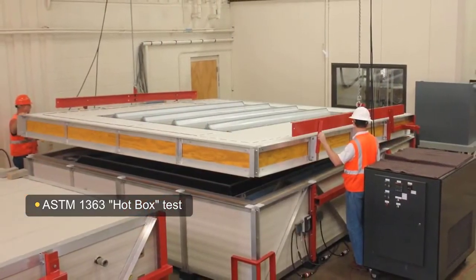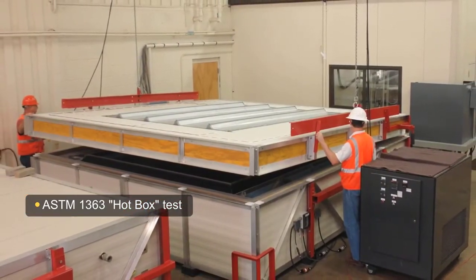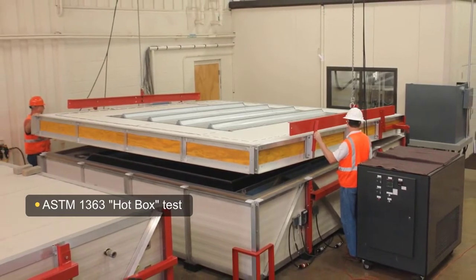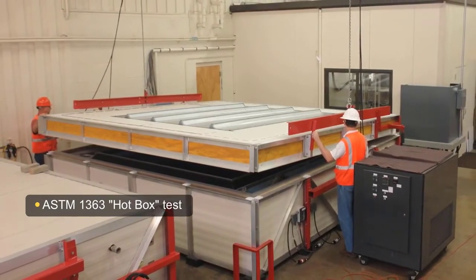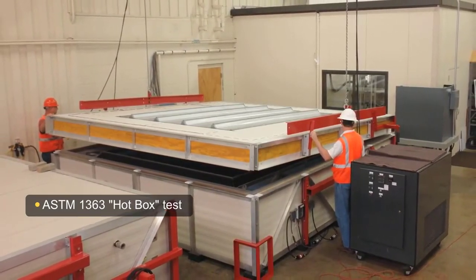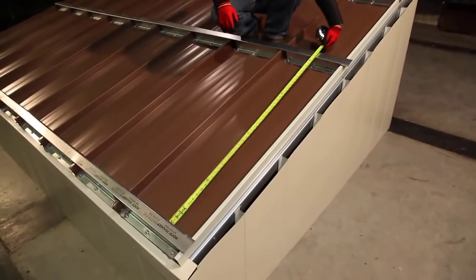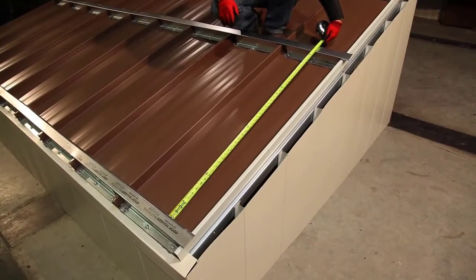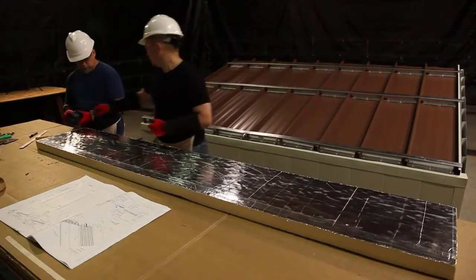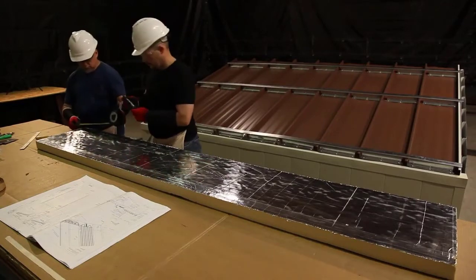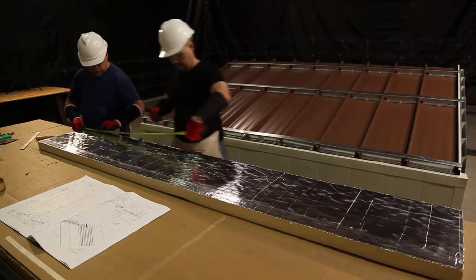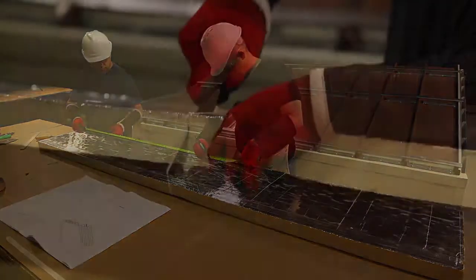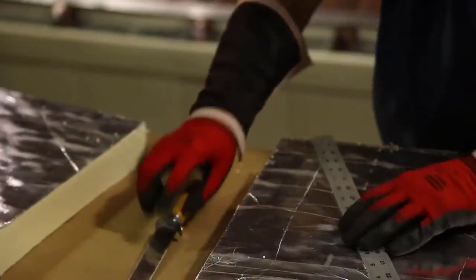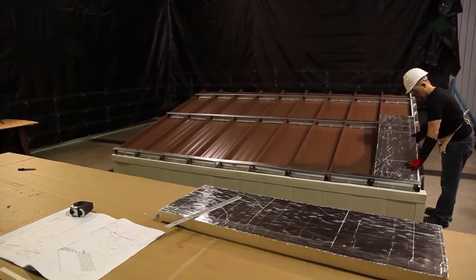A key result of this research showed that it is important to recognize how insulation systems are constructed, rather than looking only at the total R-values of the insulation layers. On our mock-up, with the sub-purlins properly installed perpendicular to the standing seams of the metal roof, a grid work of the sub-purlins to support the standing roof is formed on the roof. Using that grid work, we then installed polyisocyanurate rigid foam insulation board.